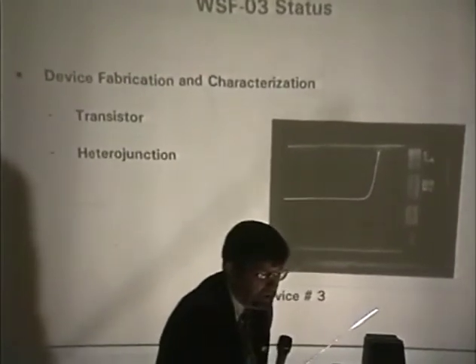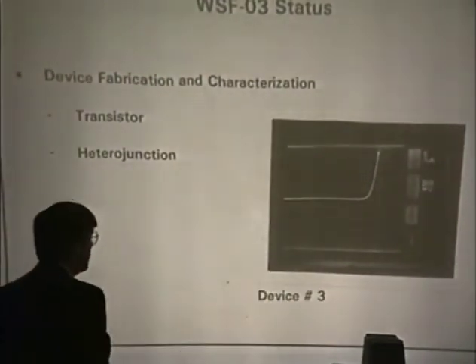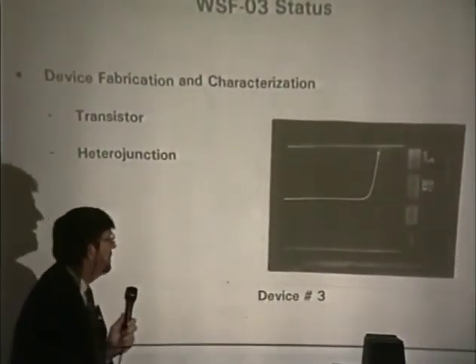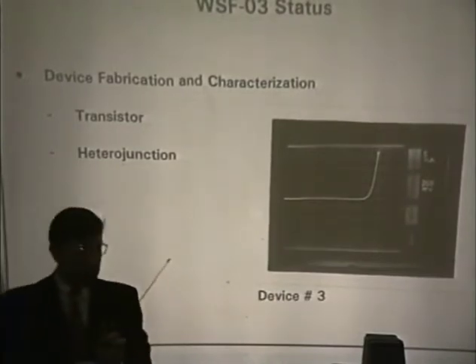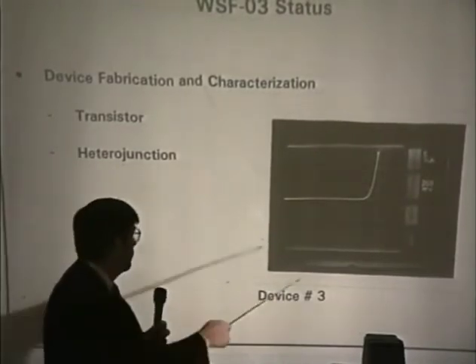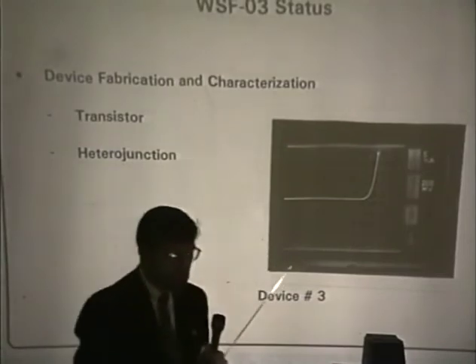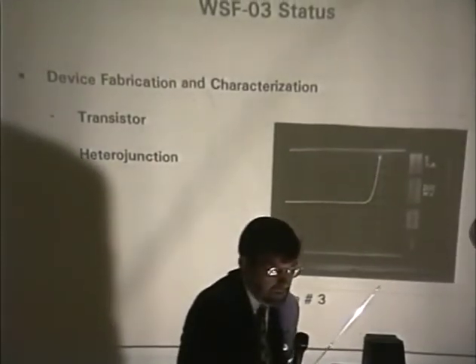And we, in fact, have made a simple junction device, a PN junction, from one of our samples that we grew on orbit. Turns out the layers that we grew in this flight are a bit thinner than we had expected. However, we're getting still some device function here. And this is then a characterization further of the environment and the applications of this environment to make real products downstream. To mention Wake Shield 4, we are working the manifest for 1999.